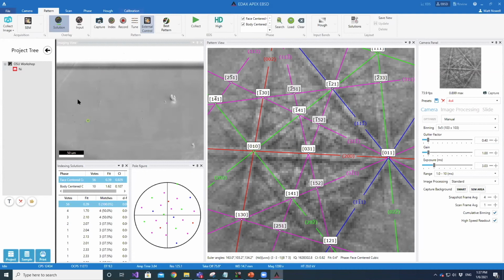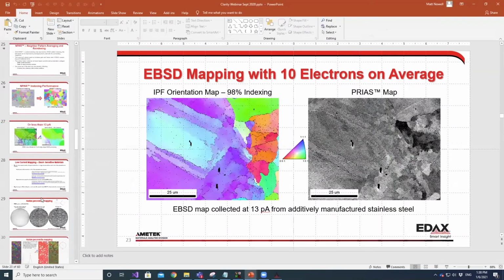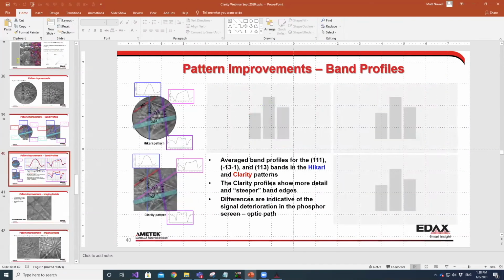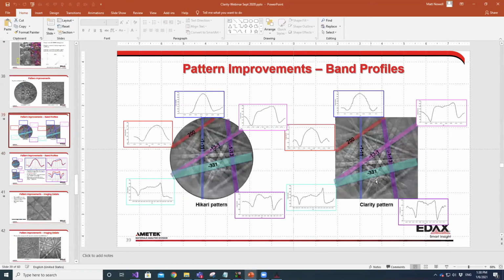And then the key with this is, again, if we look at some of the information, just if we look at profiles across different bands, there's just more contrast information through there. So we see this as a really EBSD physics type of a tool where we start to understand what the intensity profiles across lines are, and what changes in those profiles tell us. We can now measure them with more precision and more quantitative electron information. So the level of detail that's available is just significantly higher, which is really an open door to say we can really start to explore the physics of EBSD pattern formation better.